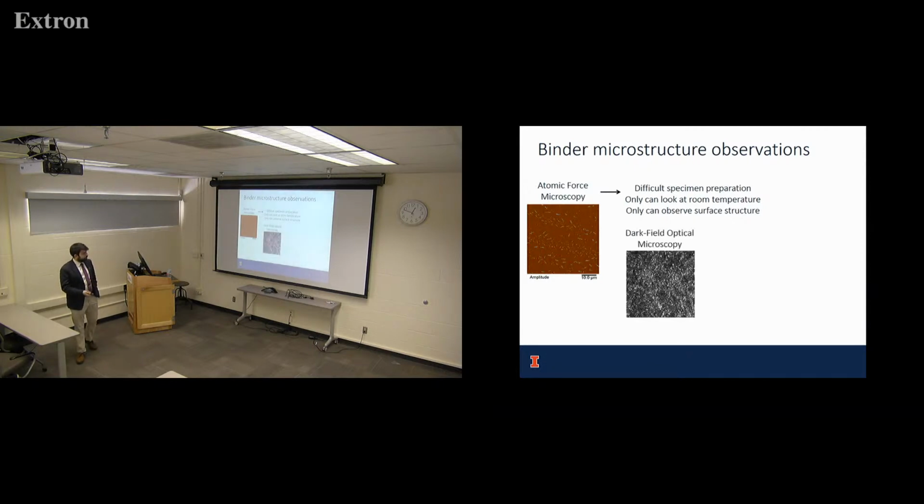So instead, we use dark field optical microscopy. We worked with a group in physics who are brilliant in optics. They helped us to use this method that scatters light at near infrared, and whatever's reflected back are those microstructures about 25 microns deep into the material. So it's not what's at the surface, it's actually what's in the bulk of the material. What we found interesting here is that those inclusions that we see are not dependent on the surface conditions. It doesn't matter if you have water, glycerin, or another solid at the surface. You could have it between two glass slides and still pick up that microstructure. So we think this is more of an inherent material property.